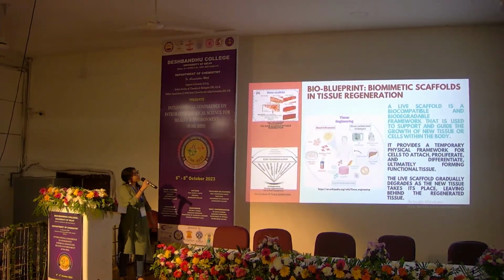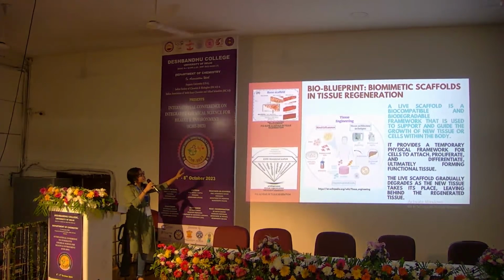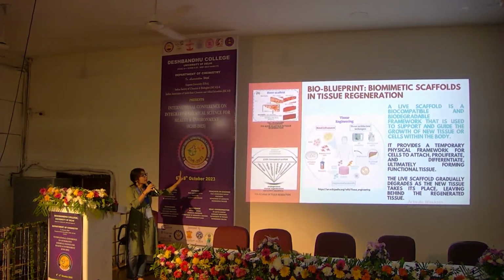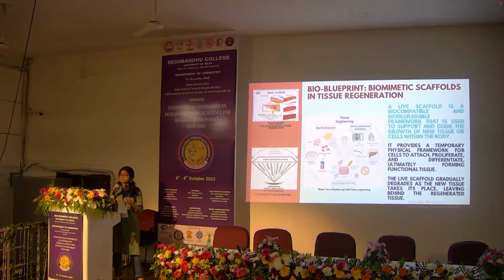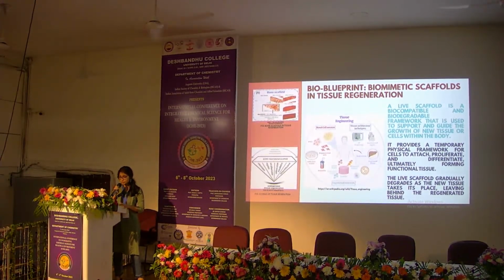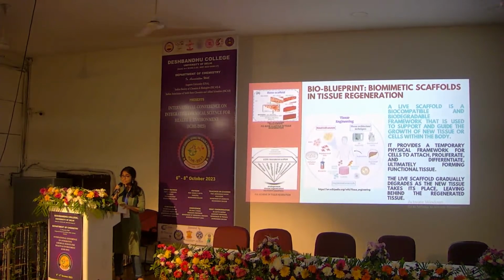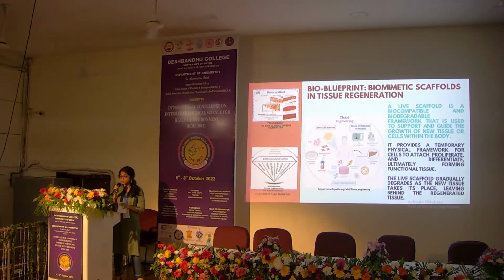In this study, we discuss how biomimetic scaffolds, or bio blueprints, have a significant impact in tissue regeneration. Yu et al., who performed this study, used hydroxyapatite crystals and 3D printing to create a porous scaffold. They tested it with osteoblast cells and found that it had strong mechanical properties. They saw a significant increase in the calcium in the scaffold, indicating that it helped with bone regrowth.